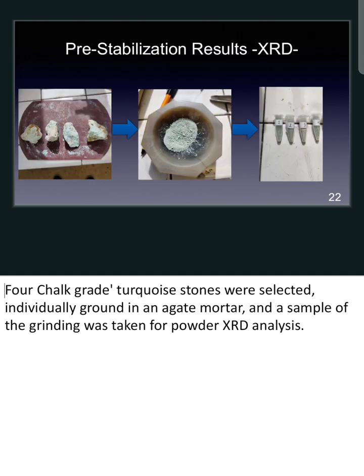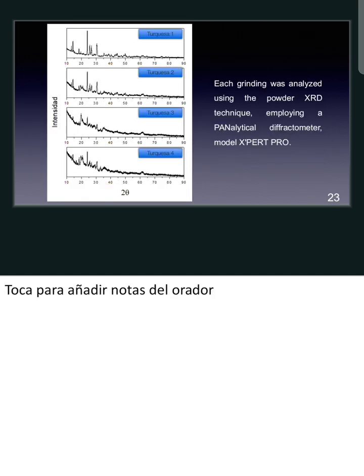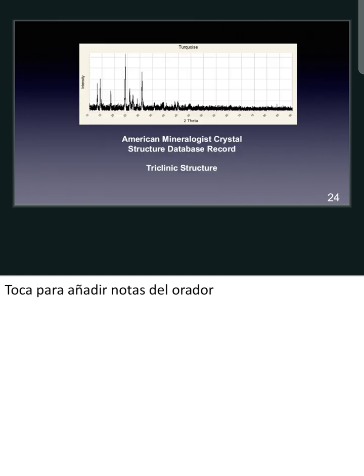Talking about X-ray diffraction, four chalk-grade turquoises were selected individually and ground in an agate mortar, and a sample of the grinding of each one was taken for powder XRD analysis. These are the results of the four samples. Each grinding was analyzed using the powder XRD technique, and we compared each result with the American Mineralogist Crystal Structure Database records, searching for a triclinic structure.